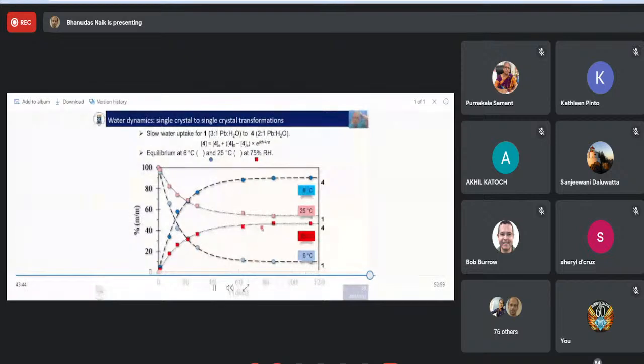So if you leave it at 25 degrees, you can see that it goes in at 25 degrees and reaches an equilibrium between the two. So at 6 degrees, you can see that you manage to get this. You can manage to dislocate your equilibrium to 4. But it plateaus at about 90% 4, and you remain 10% still compound 1.